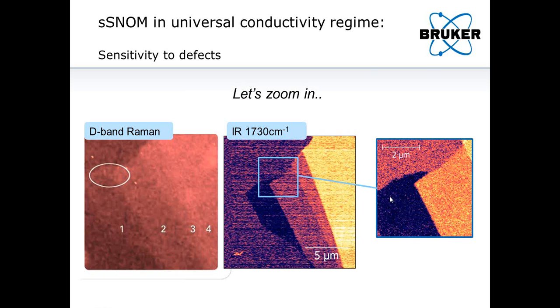Now, it's sort of hard to see, but if you concentrate on the region that lights up a little bit in the D-band Raman image, then you can see that it's a little bit darker than the rest of the graphene, of the single-layer graphene region.